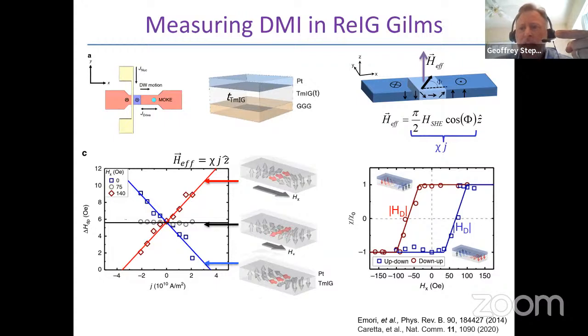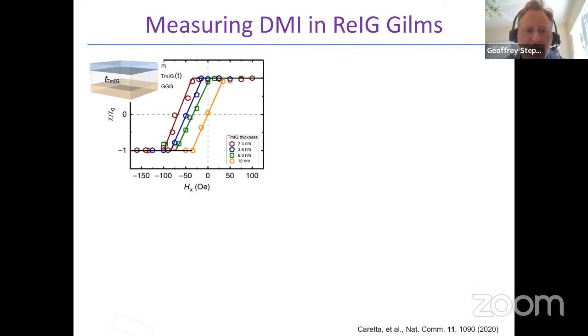Then one can apply a magnetic field anti-parallel to that, so that you rotate that domain wall from Néel pointing one way to Bloch to Néel pointing the other way. And that transition point, when you drive it to Bloch, is the point at which the in-plane magnetic field compensates the DMI. And so we can quantify it by looking at domain wall dynamics. We've done that for a variety of films. We've looked first as a function of thickness.